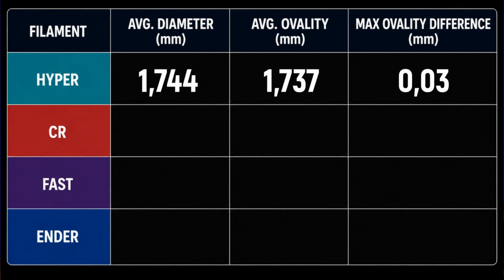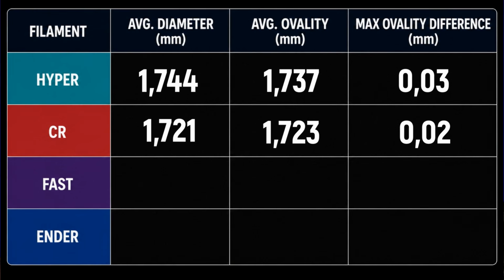When we look at Creality Hyper PLA, the average of the measurements taken from 10 different points was 1.744 millimeters, while the average ovality was 1.737 millimeters, and the difference between the ovality measurements did not exceed 0.03 millimeters. Creality CR PLA had an average diameter of 1.721 millimeters, while the average ovality was 1.723 millimeters. The largest difference between the ovality measurements was only 0.02 millimeters.